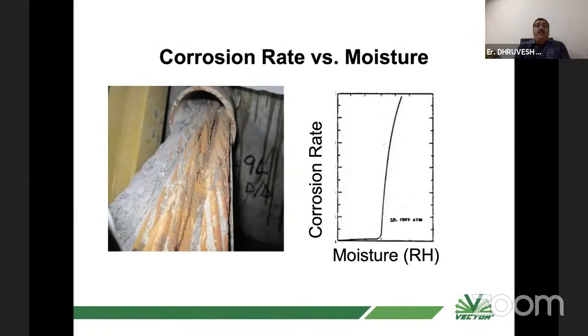Now, this is what I had talked about, the voids. Now, what is the relation of where the corrosion comes from, or how can we evaluate the corrosion rate? In particular for PT tendons, grouted tendons, you can see the corrosion rate and moisture relation, this is particularly for a standard temperature. If you had a variety of temperatures throughout a year, there can be waves like this, but the ultimate graph is simply this way. Up to some percentage of moisture, you have a very low corrosion rate, but if the moisture content increases, then your corrosion rate shoots up, and that's why even though there is very limited oxygen, the corrosion will happen. So there is a very strong correlation between the corrosion rate and the moisture, particularly in grouted tendons.